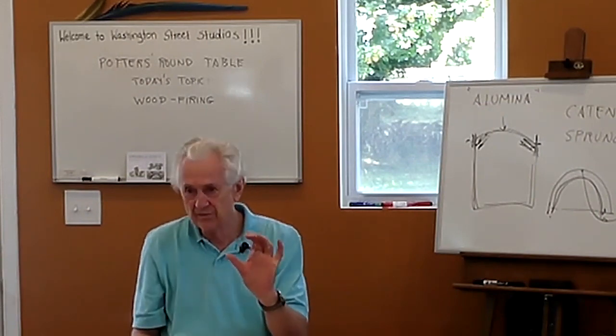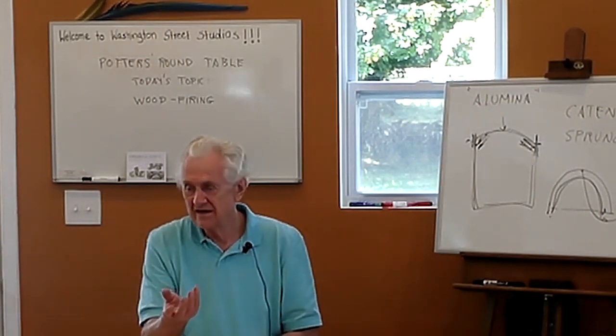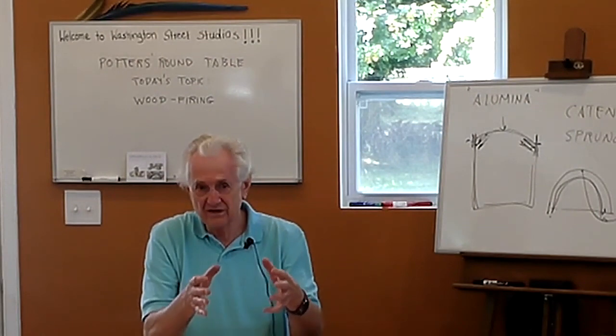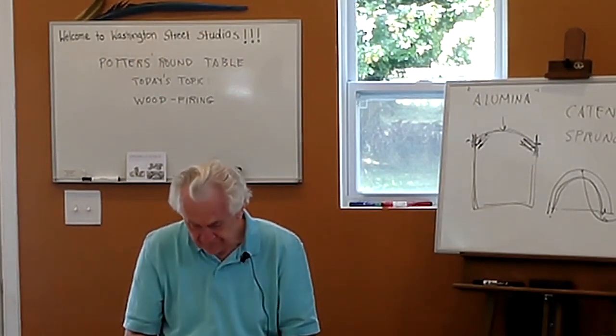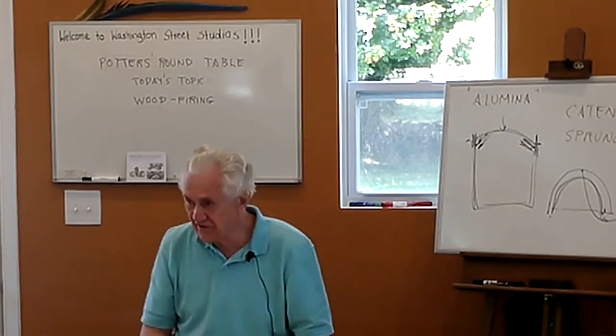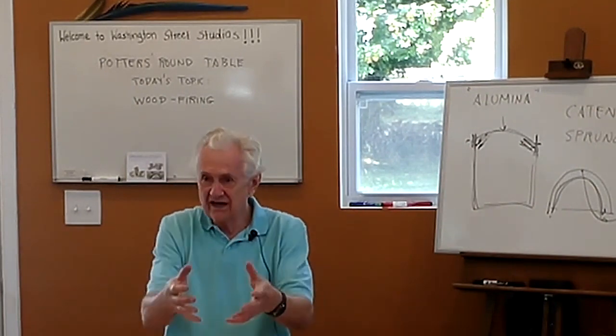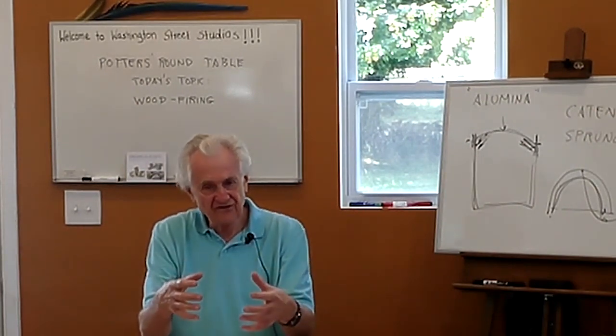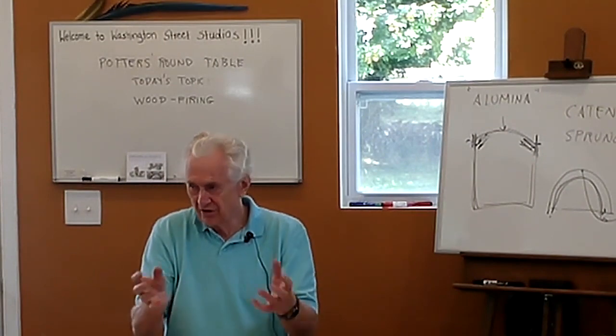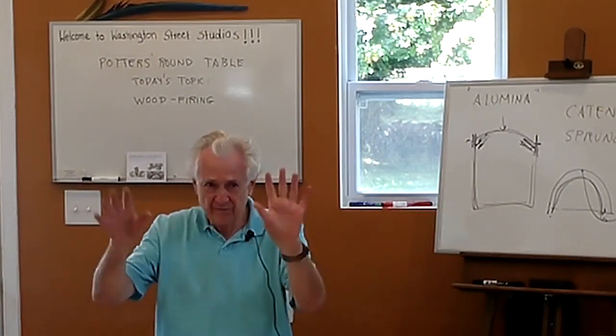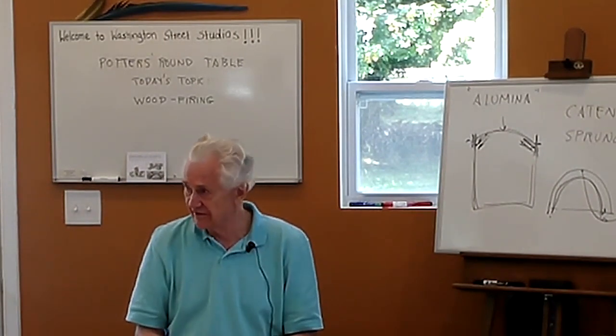I use a little raku burner, and I heat up my chimney, and then once I have enough draft, I can start to build a fire. That's where I'm actually burning the wood. Other people might just build a small campfire outside the kiln or near the entrance, and let that gradually burn and heat up the chimney so that they start to develop a draw.